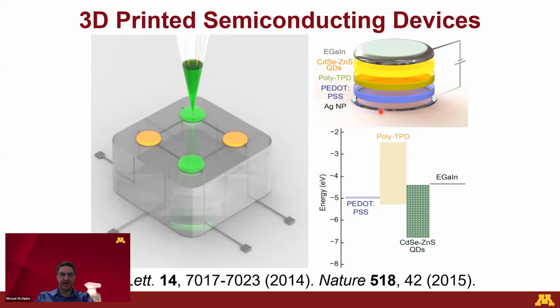So typically we use silver nanoparticle ink as our bottom electrode, and then we use 2 types of polymer conductors for hole transport, and then a quantum dot layer for, this is an LED, so that's for the light emission layer. And the top electrode has always been a little bit tricky because you need to have another contact, but if it's a metal, then you'd end up having to sinter it. Like if it was silver nanoparticles, you would have to sinter it, which would damage all the layers underneath. So what we do is we 3D print this liquid metal called gallium indium, which is a field that was essentially discovered by Michael Dickey, who was a professor at North Carolina State University when he was a grad student. So this liquid metal is just like a blob of liquid metal that you deposit on top, and then you don't have to sinter it. It basically forms your top contact, although admittedly it is a bit messy and there's probably got to be a better solution out there for that, but it's a good starting point.